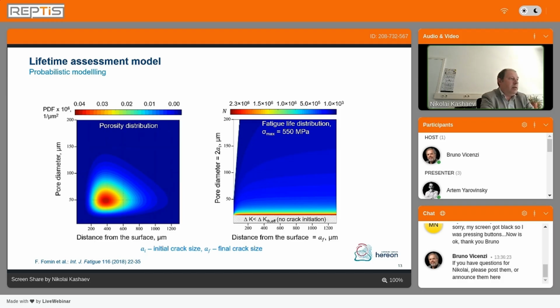And then in the right diagram, in principle, we have the situation that the color represents the fatigue life of our specimen. For example, if we consider this point with these characteristic values of the porosity, each point from the diagram on the right side can be transferred to the diagram on the left side regarding the characteristic values of these pores. And you can see that the largest pore doesn't mean that it is the critical one. The criticality of the pore is a competing situation between its size and its position relative to the surface.